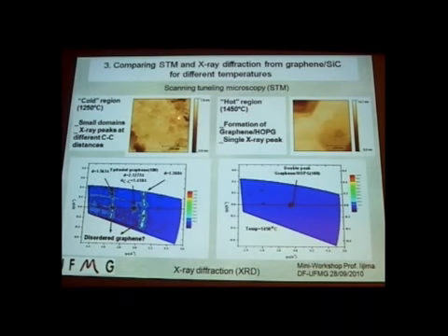If you do an X-ray diffraction, you see three peaks here coming from different origins. The first one is the epitaxial graphene, as everybody observes, but you also see two other peaks which can be associated with different carbon distances. One would be shorter than the carbon distance of hexagons, of honeycombs, and the other one is a larger distance. These results are a year and a half old, and we were scratching our heads to understand what was happening here. I'll show the explanation in the next viewgraph.